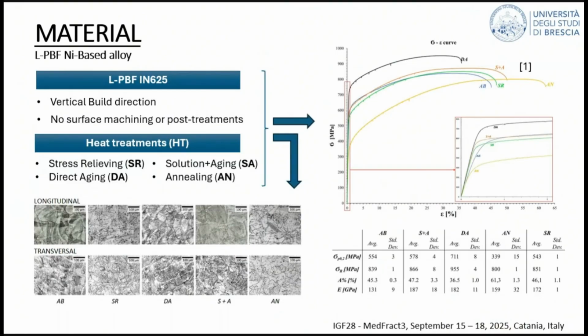We know from this previous investigation that each condition has not only a different microstructure, but very different mechanical properties. The effect of these heat treatments was to change significantly the Young modulus, the yield strength, and the elongation at break. So we have a family of different mechanical behaviors starting from the same initial condition.